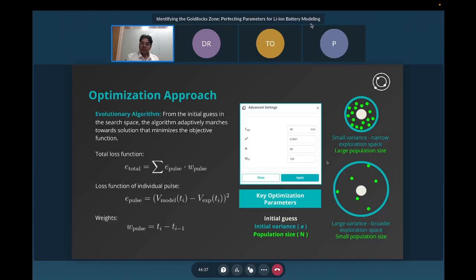Now, what we do here is that we focus on each pulse. The reason behind focusing on each pulse is that these pulse experiments are performed at a specific SOC. So you start with a fully charged cell, you do the pulse experiments, and then you slowly keep discharging the cell by 10%, and then do the pulse experiments again. Now, for each pulse profile, you will get a different kind of voltage response depending on the SOC. What we do here is that we focus on the pulses at each SOC. We calculate the voltages from the simulation. We look at the experimental voltage curves. We get the error between the model and the experiments for that particular pulse. This is our overall error.